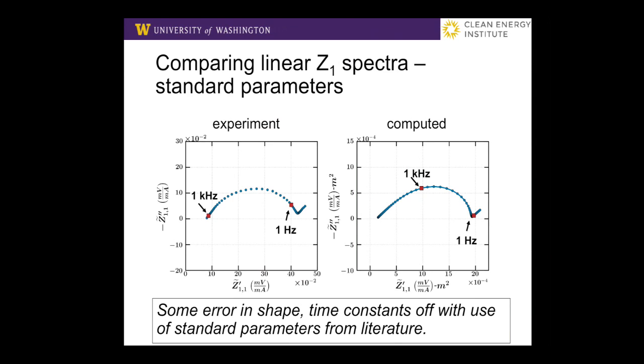All right, so let's take a look, and now we're going to mostly look at shape, because these are on a per meter squared basis, because the computed one just has the cross section. And so we're going to look at the shapes, and we're going to compare the linear response for the experiments and the computed. There's a couple of things that you can see. There's some error in the shape. For instance, at the high frequency, it's coming in at 45 degrees there, and here at the higher frequency end, it's kind of blobbing in more straight down. We see that the frequencies are off where they fit within this.